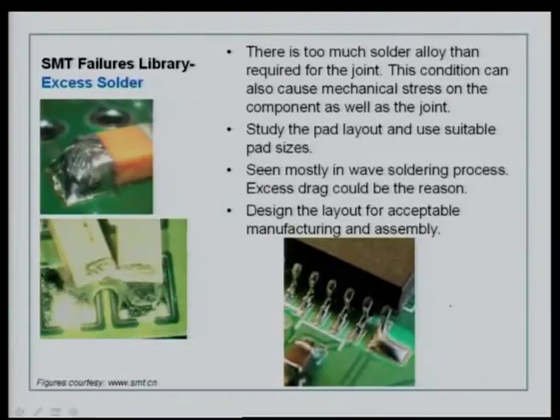The third one is excess solder. Here you can see in the picture different defects. You can see here too much solder material, there is too much solder there on the component. So, there is too much solder alloy than required for the joint. This condition can also cause a mechanical stress on the component as well as the joint. Too much solder is also a problem. So, study the pad layout, use the pad size correctly and use suitable volume of the solder paste material.